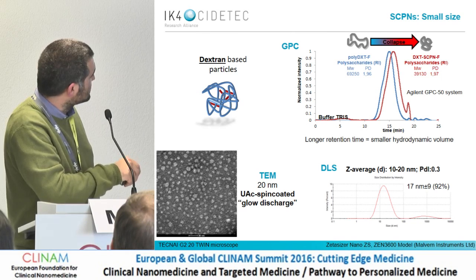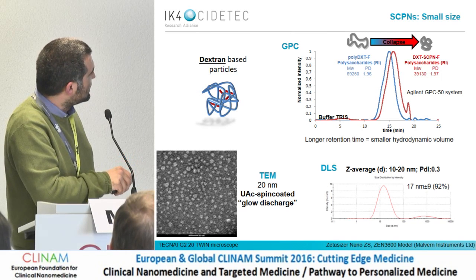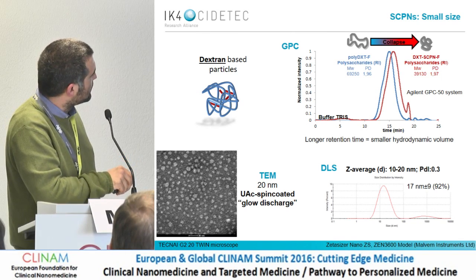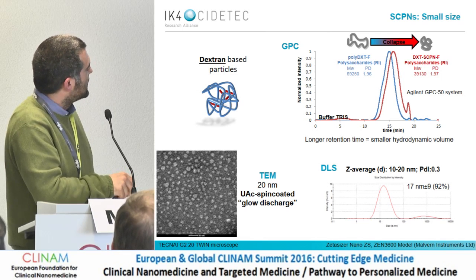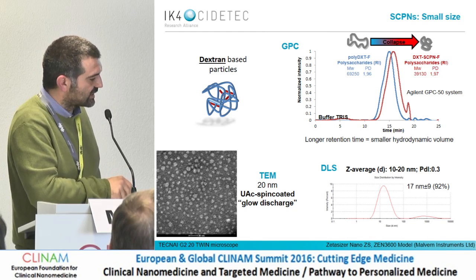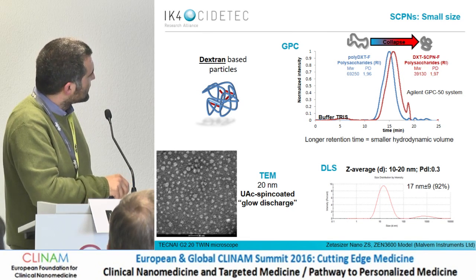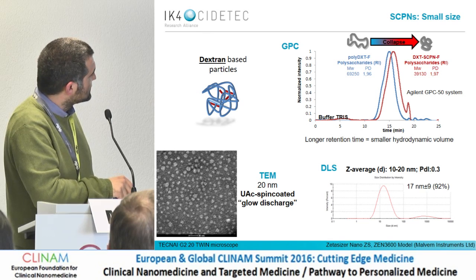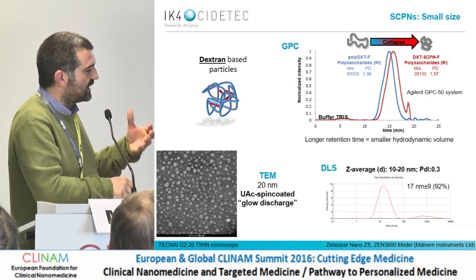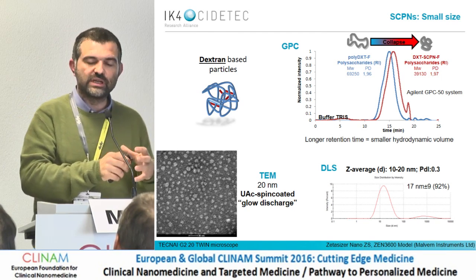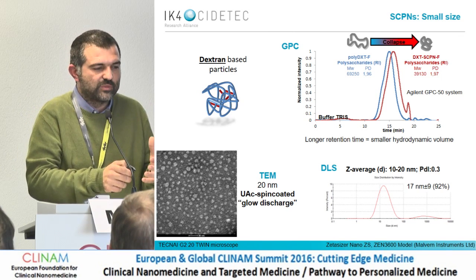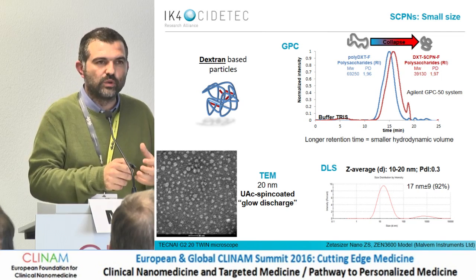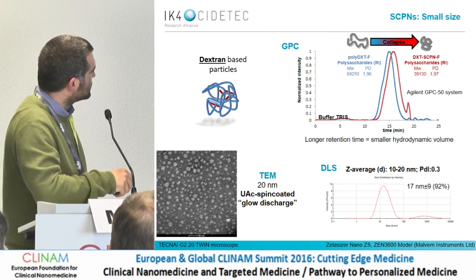We used size exclusion chromatography — GPC, gel permeation chromatography — to verify whether the collapse from polymer to nanoparticle was efficient and real, and whether we had any inter-cross-linking. The retention time of the nanoparticle is much longer than the polymer, indicating a smaller hydrodynamic volume of the final particle. This gives an indication that the apparent molecular weight is lower, confirming the shrinking to a nanoparticle.